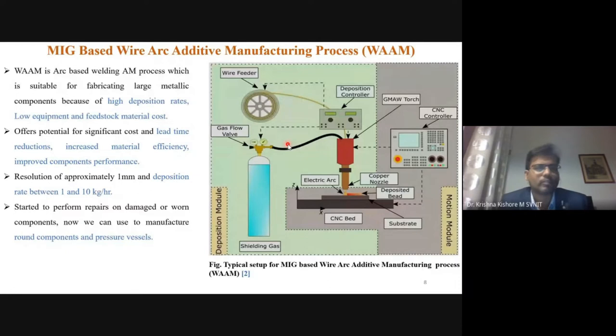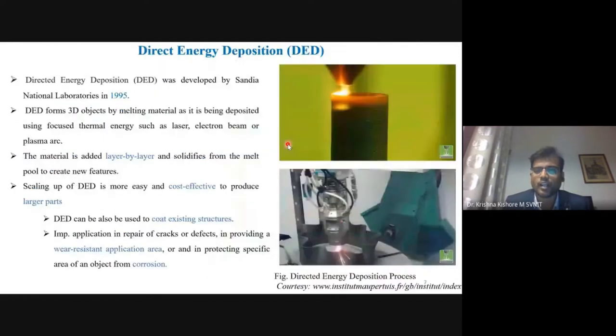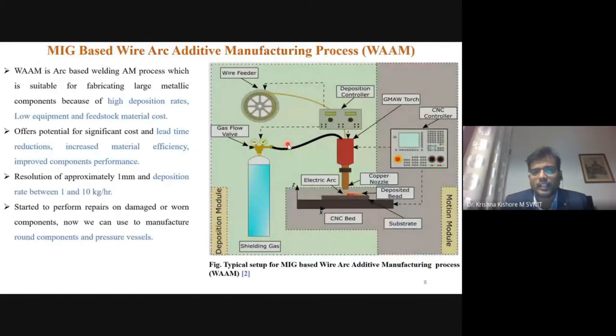So people have thought of developing some process which is quite cheaper and can achieve a much higher deposition rate. And one more disadvantage is that the bed size in direct energy deposition depends on the capacity of the machine, and the component size is restricted by this bed only. So the component size we achieve in the direct energy deposition process is entirely dependent on the machine which we have. And in the case of wire arc additive manufacturing, people have developed this process to break this